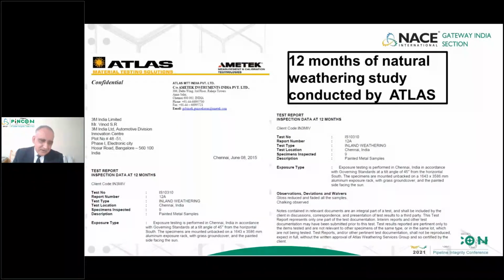The dual layer is also tested for weathering resistance by a company called Atlas, which is known for natural weathering. They have evaluated fields for 12 months of natural weathering, even if the pipes are lying on the dump site and exposed to natural weathering, even in sites like Chennai, which receives very high UV light. The coating remains unaltered. It does not deteriorate. After 12 months of weathering, these panels were tested again for the original specification like adhesion, flexibility, and impact. The only observation was that the glossiness of the coated panels faded a little bit. There is a color fading effect after 12 months of exposure, but there was no deterioration in performance.